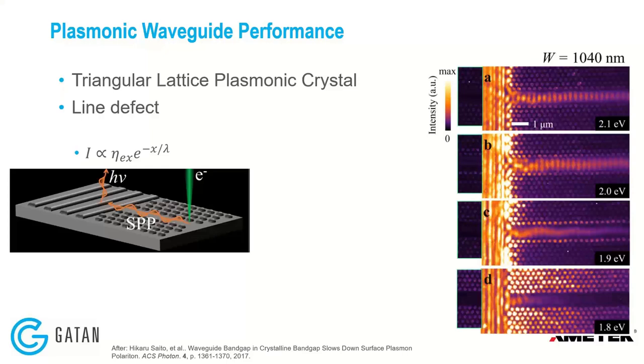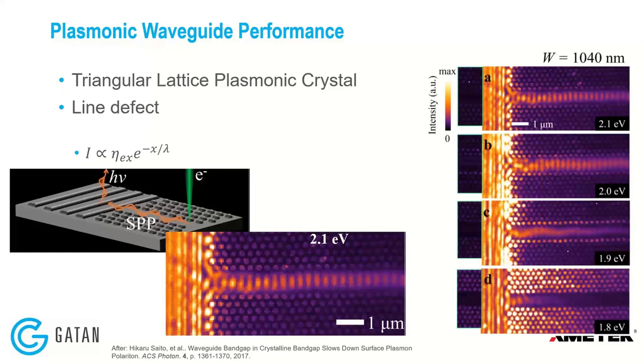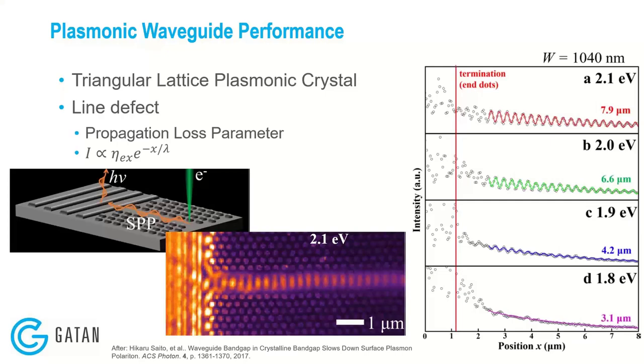If you introduce a line defect in such a plasmonic crystal, you allow the coupling of surface plasmon-polariton guided modes — essentially generating a waveguide. The behavior differs depending on what wavelength you're observing. Looking at CL images, you can see the intensity across the surface; in the waveguide you can see standing waves that decay off to the edges. An interesting measurement is the propagation loss parameter: by taking a line plot of intensities down the waveguide, you can determine the rate of decay and assess the feasibility of using this structure as a waveguide.